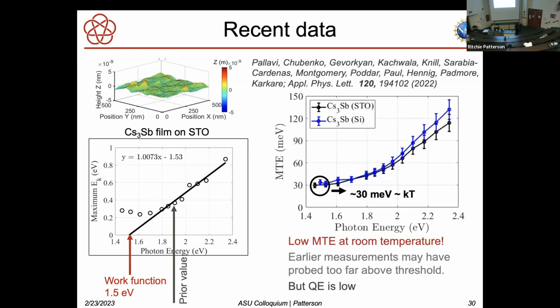When they make their MTE measurements going all the way down to this lower threshold, they see 30 millielectron volts, which is within measurement errors of kT. So this is very interesting, and it's very exciting to see low MTE at room temperature. It's the first time that's been done. There's the caveat that the quantum efficiency is low, so there's more work to be done, but this is a very exciting advance.